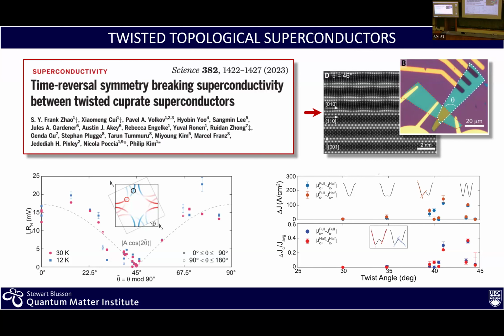Now here for the experts, it gets a little complicated, but here you have a function of angles, 45 degrees being one layer and the other are really opposite by 45 degrees. What you're looking at here is the tunneling current between the two layers, and it is a superconducting tunneling current. The linear term of that will go to zero at exactly 45 degrees. So the linear term in the tunneling current, the Josephson current, will go to zero at 45 degrees. And that's what one expects. And so this is the proof that the junction that is being made there is a superconducting junction, and what you're seeing is incoherent tunneling between two d-wave superconductors.